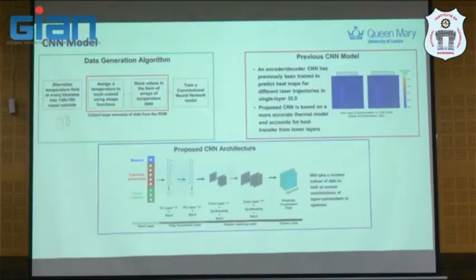And the next step, once we do this and we believe this is good, is we can build a data generation algorithm from that. Rapid calculation, I would say, like what I showed you before. And then we generate this data, combined with some understanding from our previous CNN model here, to capture this, the measured and the predicted here. We try to do the same here using the CNN architecture, where we learn from the data and process parameters, laser deposition pattern and so on, and then use deep learning to get the predicted temperature field. Again, this is based on the image that you get from the result, or if you want to extract from the coordinates in the data, that is also possible, but it depends on how powerful the code you write to make this possible.